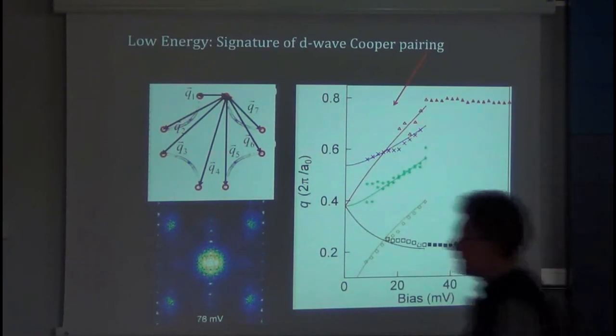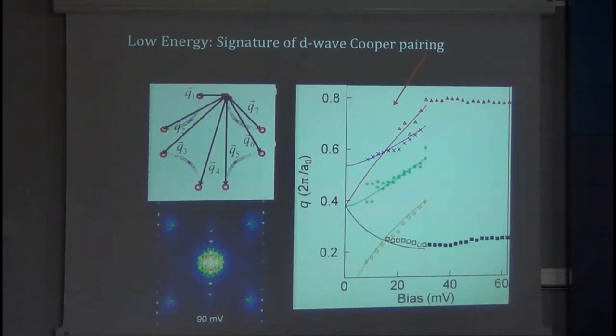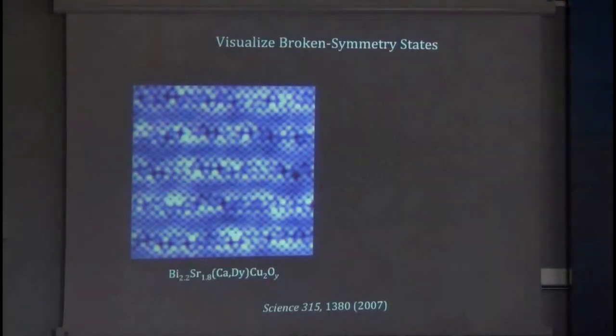Now we know exactly what the low energy piece is. It's the quasiparticles of the D-wave Cooper pairs in the system. They're in really excellent agreement with theory. These solid lines here are the theory, and these data points are the data. So it's beautifully consistent with the signature of D-wave Cooper pairing. The high energy piece, which does not change with energy, actually appeared very mysterious to us in the beginning. These high energy states here are wave functions which do not evolve with energy, and they have several broken symmetries, which I'll show you right now.